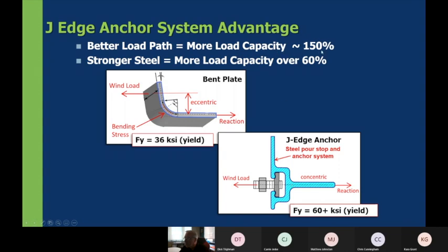Because of that, we have a greater capacity, about 150% increase in capacity just because of the better load path. In addition to that, we have stronger steel, which equals more load capacity, about 60%. So the traditional bent plate would be about 36 KSI yield strength. Due to the new extrusion techniques that they have, this is 60 plus KSI material for J-Edge anchor system. And so this is a 60% increase. So these two items together give over 200% increase in capacity over the traditional bent plate pour stops that we see.